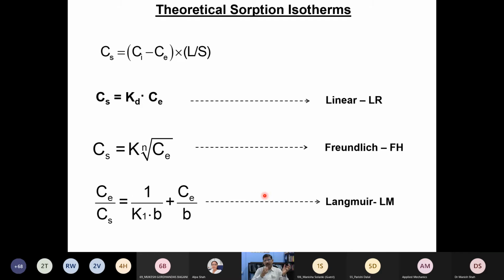At the end of the day, initially you have a certain concentration in the leachate, in the solution phase, and a certain concentration at the end of the interaction time, which is the CE. The difference between the Ci and Ce is basically what has been transferred into the solid phase, and multiplied by the liquid-solid ratio, it gives me the concentration in the solid phase. Once I know the concentration in the solid phase and the equilibrium concentration in the liquid phase, if I correlate these two parameters linearly, it's called a linear sorption isotherm, where you call it a KD parameter. If it's non-linear, we may say that it's a Freundlich isotherm. If it's something else, we may see a Langmuir isotherm.